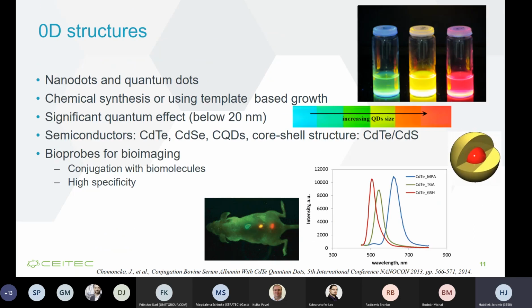And the last part focuses on nanodots and as well quantum dots, which are more on topic. So this is for biosensing. We used several chemical synthesis or template-based techniques to grow these nanodots. The quantum effect is observed in some materials when the size is below 20 nanometers. And by the size of the quantum dots, we also change the wavelengths of the emission. Mixed semiconductors are used in synthesis. So we created cadmium telluride or cadmium selenide quantum dots, as well as carbon-based quantum dots.